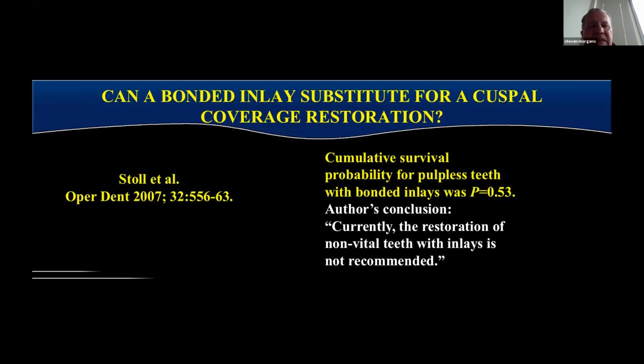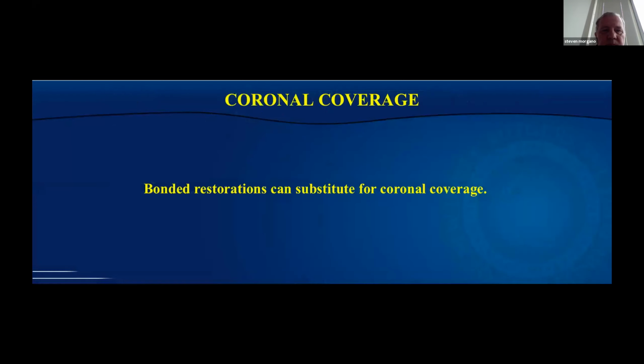Now, there's not so many clinical studies on bonded inlays, but this one by Stoll was a study on bonded Empress inlays. And they separated out the inlays that were endodontically treated. And the probability of success was 53%, which means almost 50% failed over a 5-year period. So the conclusions were currently the restoration of non-vital teeth with inlays is not recommended. So bonded restorations can substitute for coronal coverage? That's a myth.